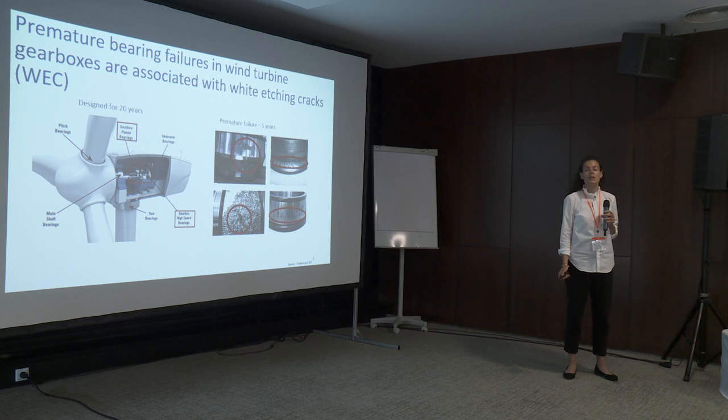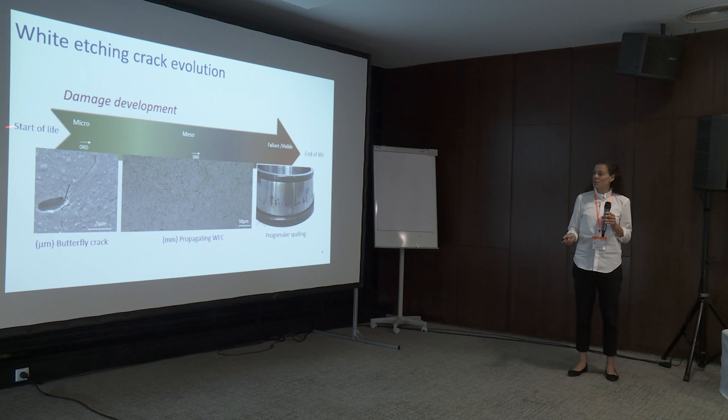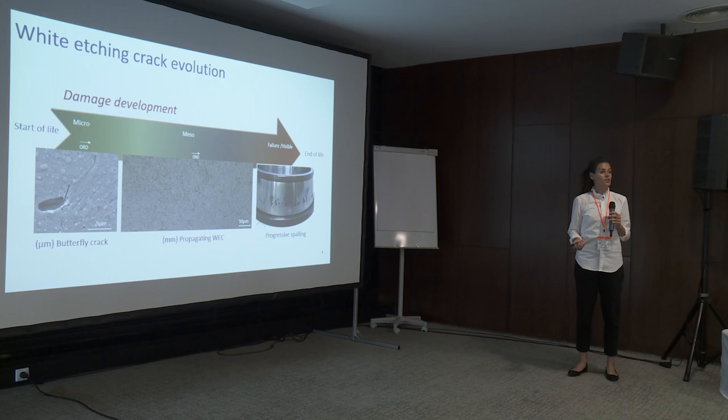This is how they look like when they are out of service. On the microstructural level, failures usually start on a defect in the material, like non-metallic inclusions, then they tend to propagate and form crack networks, and once they reach the surface of the bearing, they cause failure.